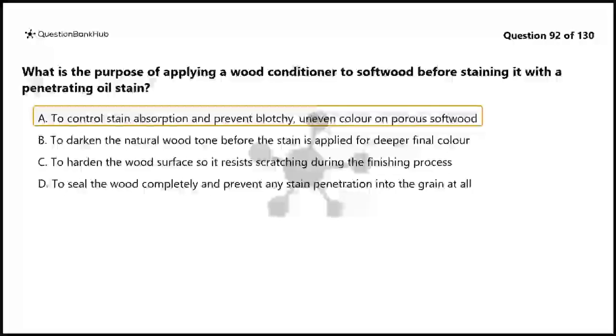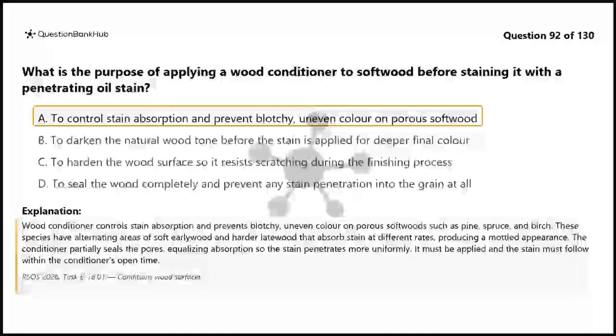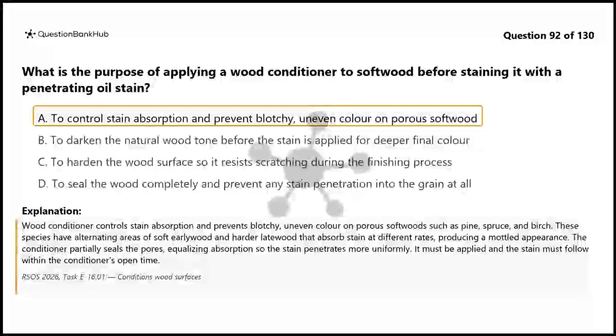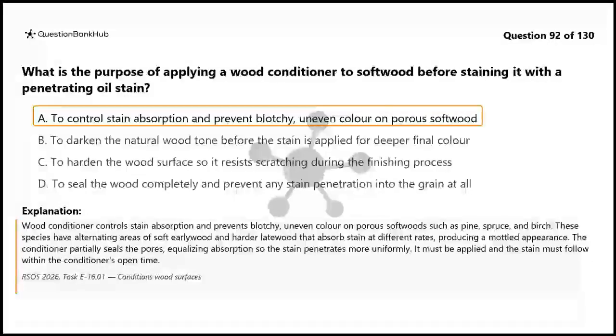The correct answer is A. Wood conditioner controls stain absorption and prevents blotchy, uneven color on porous softwoods such as pine, spruce, and birch. These species have alternating areas of soft early wood and harder late wood that absorb stain at different rates, producing a mottled appearance. The conditioner partially seals the pores, equalizing absorption so the stain penetrates more uniformly. It must be applied and the stain must follow within the conditioner's open time.